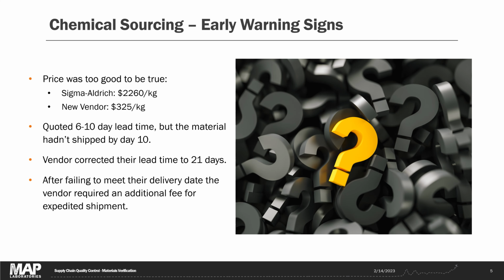So we ended up finding a new vendor. I'm not going to mention them by name, but there were a couple indications that this wasn't going to work out. One is that the price seemed too good to be true. It was about 15% of the Sigma Aldrich price. They quoted a 6 to 10 day lead time, but then failed to meet that lead time, failed to meet the requoted lead time. Things were not looking good.